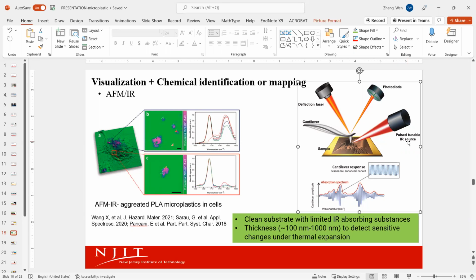Basically, you shoot a laser, and certainly you can choose the laser wavelength, the light wavelength. You can choose a pulse signal, the frequency, something like that. So you can generate basically a pulse absorption of IR. So instead of measuring, as FTIR or Raman rely on, the IR signal absorbance or transmission, right? Depending on the thickness of the sample.